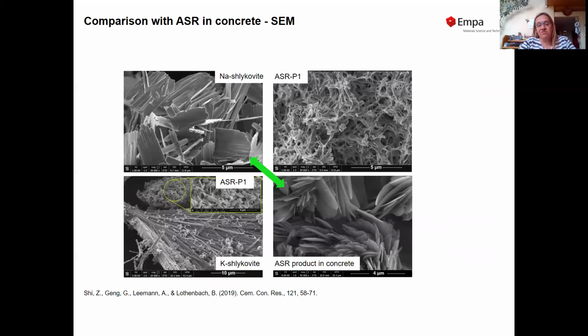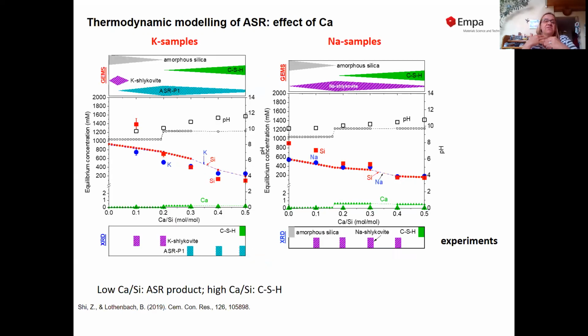We can look at the morphology, and depending on the presence of sodium and potassium, they can have quite a similar morphology to the one we observe in concrete, or in the absence of sodium, they also can have a somewhat different morphology. We also have measured aqueous solution. We have known or measured the composition of the solids, and based on that, we were able to derive thermodynamic data. Maybe we just concentrate here on the sodium example.